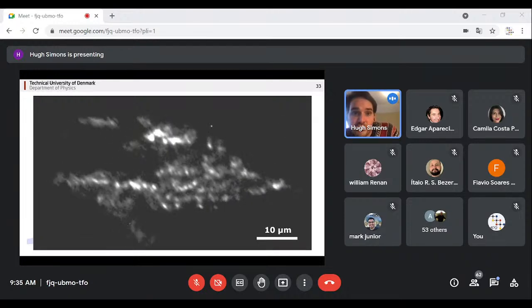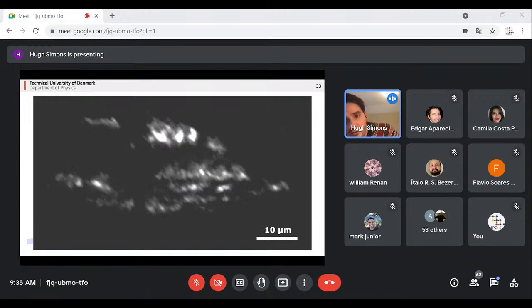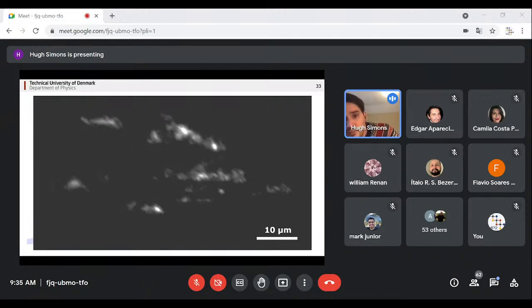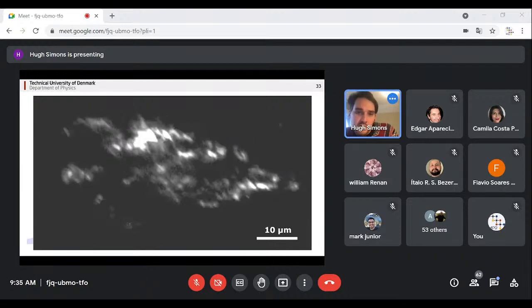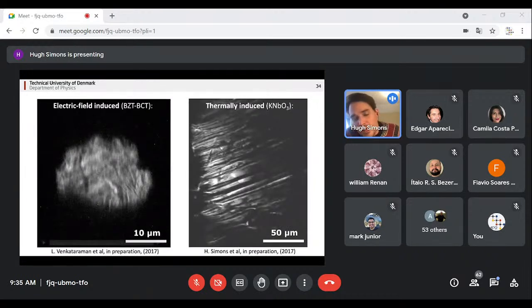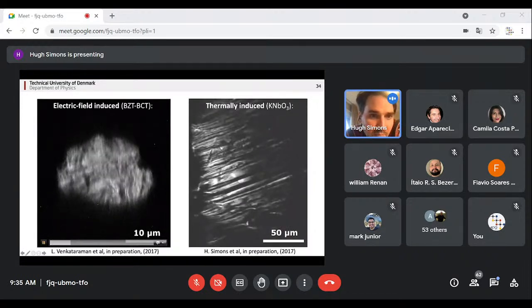So you can see the intensities changing as the domains go from one orientation type to another. And so now they're disappearing because they're moving into a different orientation, which is outside of the Bragg condition. We're also able to make these kinds of videos on other material systems just out of interest. This shows an electric field-induced phase transition in another ferroelectric called BZT-BCT.